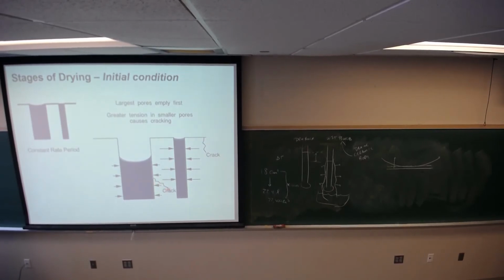You should recognize in ceramics that we always fail in tension, right? So that means your stresses are going to be perpendicular to this crack direction. It is in the direction of that smaller pore. What's the problem? Well, it implies that I'm always going to get some sort of cracking in the drying of a ceramic body, and that's not what we typically see. Okay? The other thing is that this would imply that I create cracks that then limit the strength of the system. That doesn't appear to be what we see either.